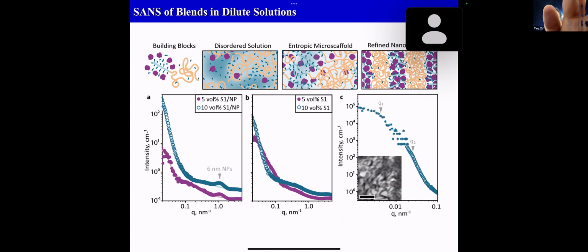But nevertheless, with the system we have here, figure A is the 5 and 10% small angle neutron scattering in deuterated chloroform with the presence of nanoparticles. The signal is weak, but we really rely on the contrast match of the various components to tell us what things are. So when we fit the data, what we see is that at five volume percent, there is a little bit of molecular aggregate, but overall the particles are randomly distributed.